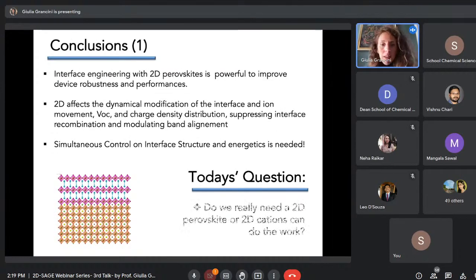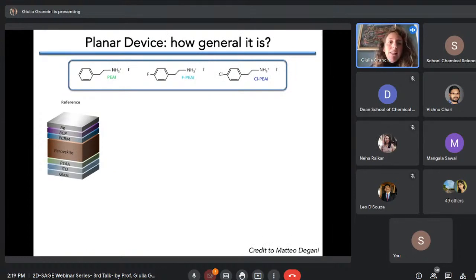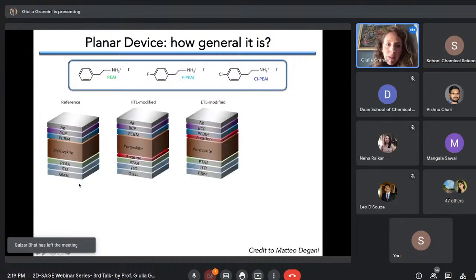So what we added here is a different method. Basically, this is always the solar cell with the 3D perovskite in the middle. This is the PIN configuration. And what we wanted to do here is to passivate both the bottom surface and the top surface. So before we had just the top surface passivation, but we form clearly a 2D perovskite, and we see the formation of the 2D from XRD and from PL emission.